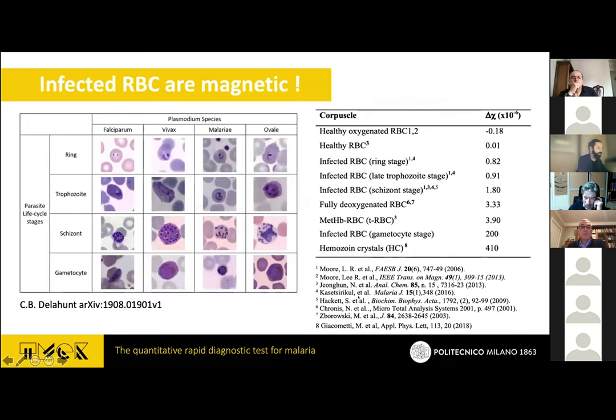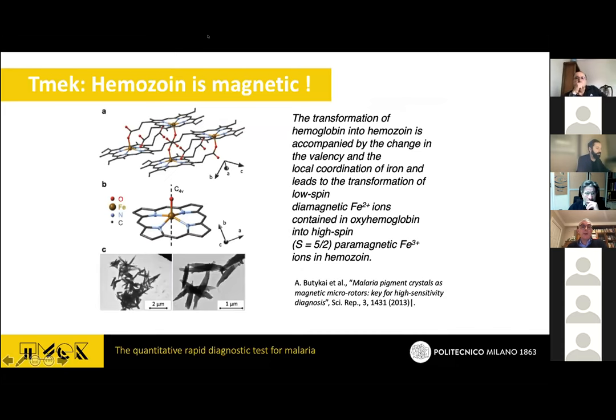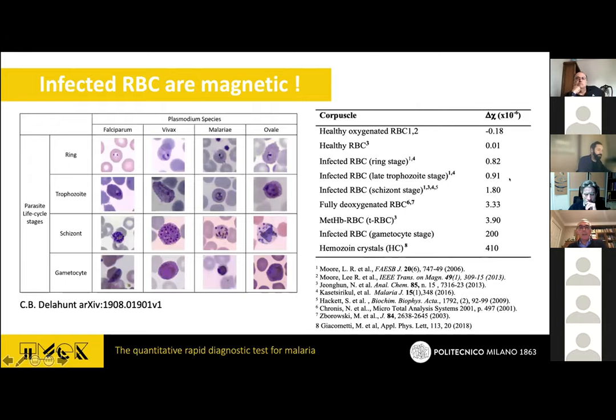So what we did was to figure out what you could do using the magnetic properties of the hemozoin crystals, which are due to the transformation which happens in infected red blood cells. This transformation creates hemozoin with a change of the valence state of the iron, which is contained in this molecule here, which is essentially the heme, so that you have a transition to high spin states, iron 3+, which means that you are dealing with a paramagnetic material. So the susceptibility is very, very tiny. For an infected red blood cell, you are on the order of 10 to the minus 6, which is the delta chi with respect to the water, and which is not very good.